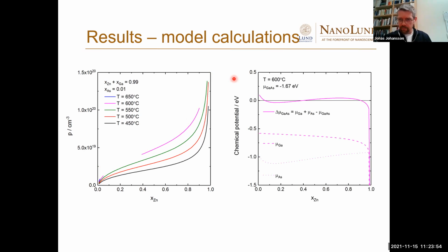So if we plot the chemical potential for gallium arsenide, we see that between these zinc concentrations, the chemical potential is negative, so no growth here. But at these concentrations, we can still grow. So at this temperature, I just hit the 0 line here. So therefore, we have these apparently non-linear effects in where we can grow or not.